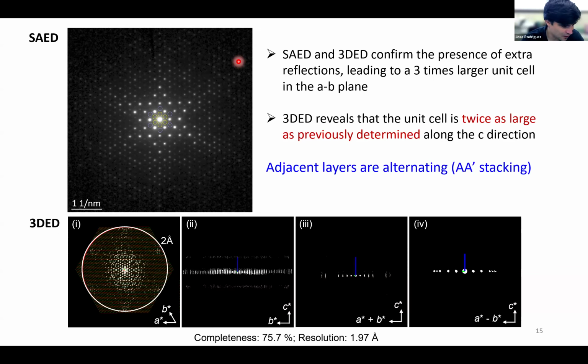Because this goes back to your previous suggestion. I think this might be a really interesting material to try that on, to basically collect a very, very low dose electron diffraction data set, in the conventional continuous rotation micro-ED style, and then with the ptychographic reconstruction that you get, try to see if you can seed phases.